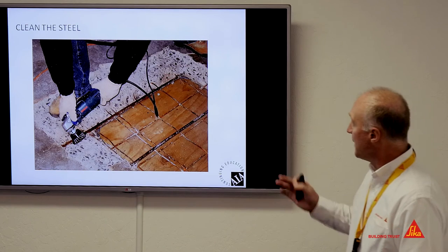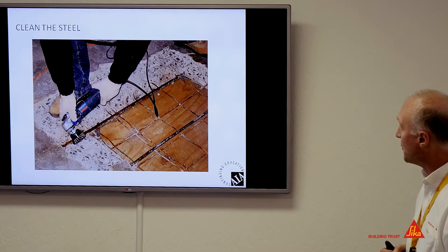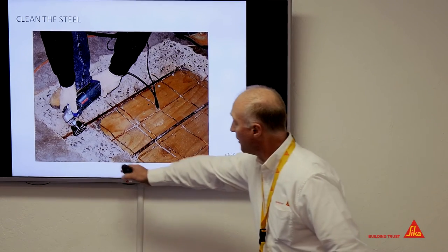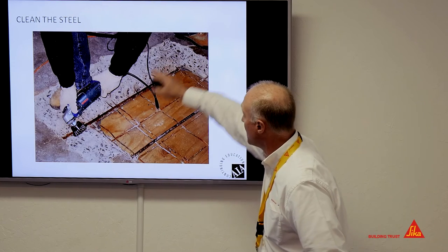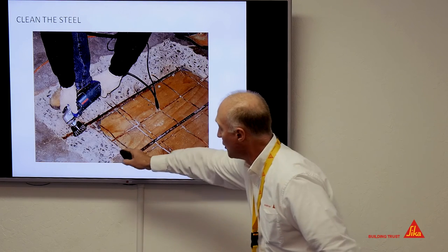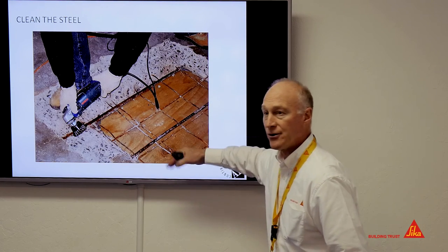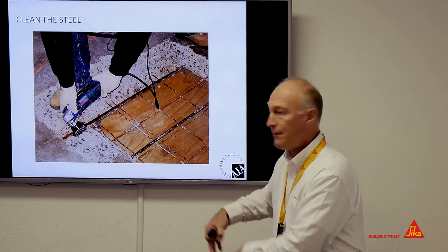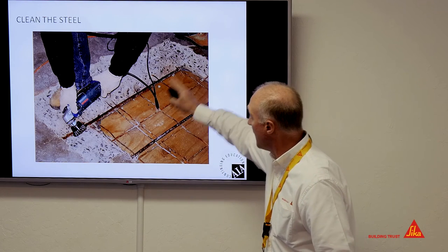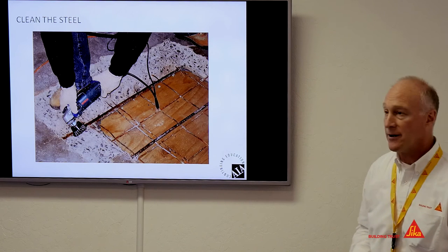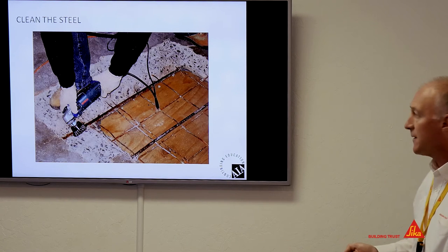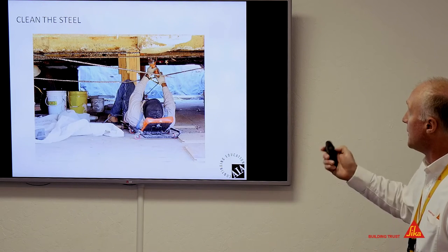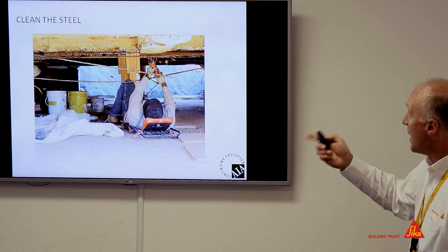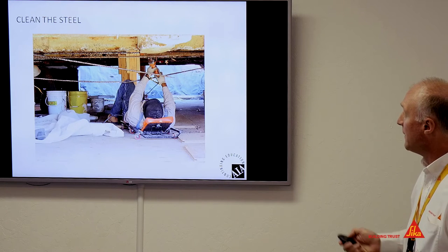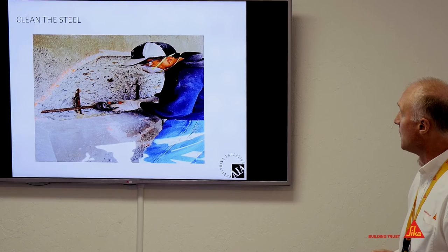Now that the steel's been exposed, this is a pretty good job here. The area's been excavated around and chipped out. This is a full depth repair, so they've taken it all the way through the slab and they're forming this. Now they'll remove all the rust product on the steel and get the bar nice and clean. This is actually at Lake Merritt. They were grinding the steel here and prepping this before placement of the concrete repair.